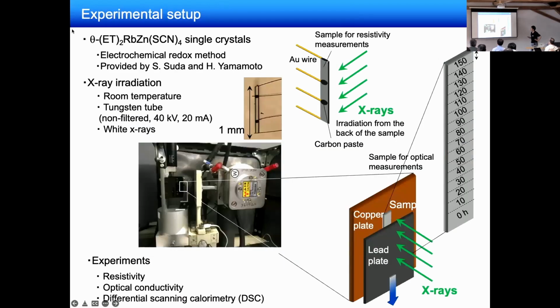Okay, so this is the experimental setup for X-ray radiation, and we used a tungsten tube to irradiate X-rays to the samples. And we measured the resistivity, optical conductivity, and DSC measurements for the X-ray irradiated samples. For the optical measurement, we changed the irradiation time in the same sample by changing the lead plate, which works as a protection against X-rays.